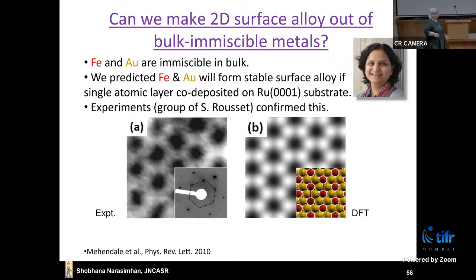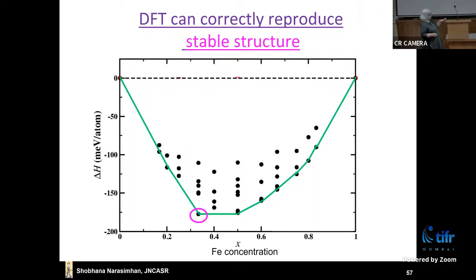Okay. Now, the interesting thing is, though we thought that this system would form a surface alloy, this particular structure was something we hadn't tested. We hadn't realized this would be the ground state structure. We had tested some other structure. So after they showed us these experimental results, we went back and calculated a bunch of other structures. I won't go into the details of what this plot shows. It's something called heat of formation or enthalpy of formation. And the important thing is just that the most likely structure to occur is what's circled in pink. And that structure corresponds to the one that's observed experimentally. So experiments and calculations agree about what is the most likely structure.